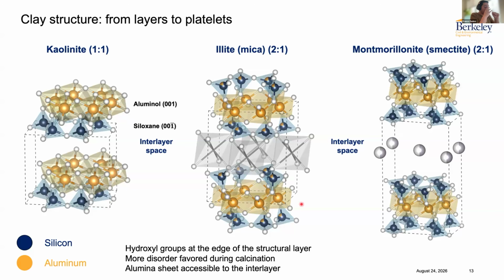So before moving to calcs and clays in particular, a brief introduction on clays. Clays can be minerals of different groups. In general, we are more interested in the clays of the kaolinite family, or one-to-one clays, where we have one aluminol sheet per one siloxane sheet. That's why we call them one-to-one. And the particularity of this is that the aluminum and the silicon are exposed through the interlayer space, whereas in 2-to-1 clays, we only have silicon exposed to the interlayer space. And that has an effect on the dissolution kinetics of these materials. Again, surface is the difference. It's really not just the bulk.